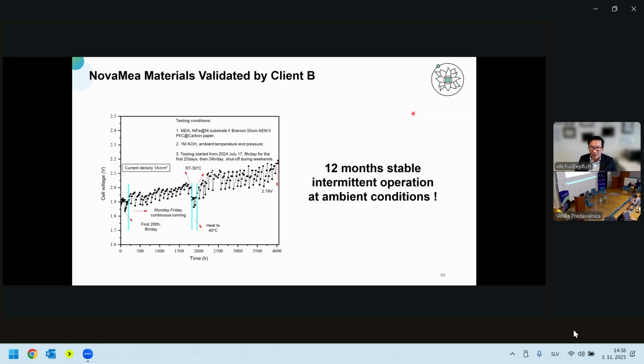We also have one client that tested our membrane for 1 year, and it was stable, but also, importantly, under intermittent operation at ambient conditions. The way they do it, they sometimes decide to run Monday to Friday continuously, or they start it and stop it, or they run 8 hours per day and then stop it. This is a good mimic for an intermittent study. And they don't control the temperature, so you can see the voltage can be high and low depending on whether it's summer or winter, and whether they control the room temperature or not. But the main point is that this has been run for a year and it's still working,